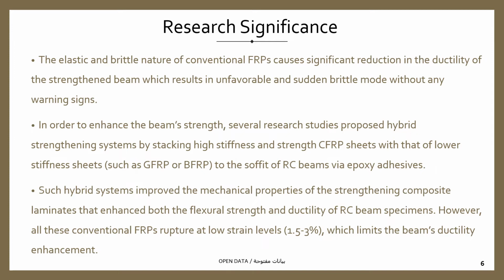In order to enhance beam strength, several research studies proposed hybrid strengthening systems by stacking high stiffness and strength CFRP sheets with lower stiffness sheets, such as GFRP or BFRP, to the soffit of RC beams via epoxy adhesives. Such hybrid systems improve the mechanical properties of the strengthening composite laminate, which enhances both the flexure strength and ductility of RC beam specimens. However, all these conventional FRPs rupture at low strain levels from 1.5 to 3%, which limits the beam's ductility enhancement.